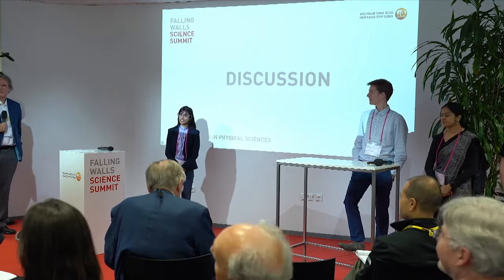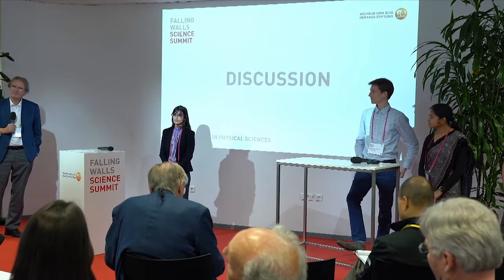Yeah, my question is to Poonam. So you showed that when you change the electric field, there is a broadening of the absorption spectra. So why is that? So this is actually called the Stark effect, which is very widely studied. In the case of the Stark effect, the broadening is because you have these molecules which are aligned either parallel or anti-parallel or in different orientations. And because in molecular systems the orientations are random, when the dipole moments are randomly oriented, it actually leads to a broadening in the spectrum.